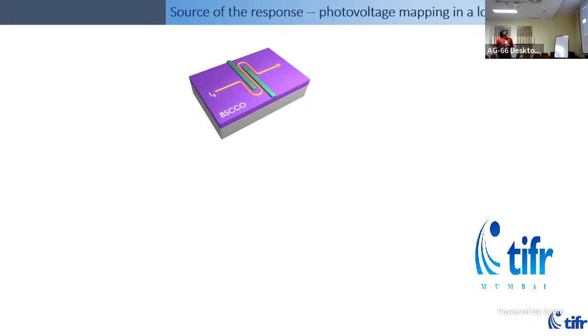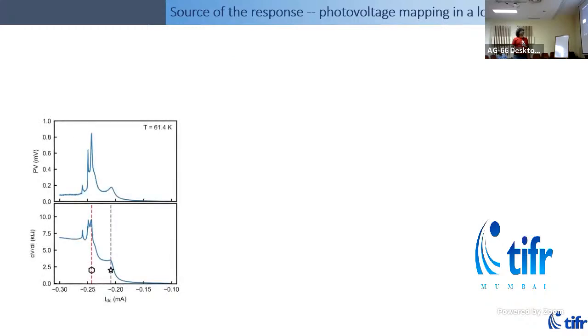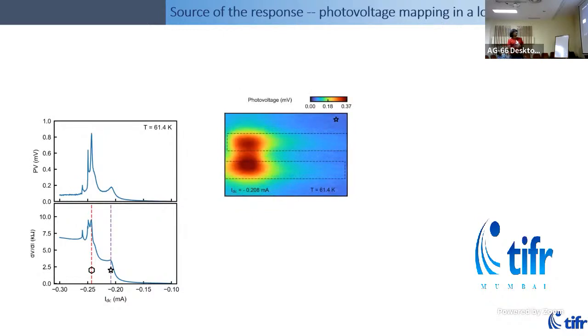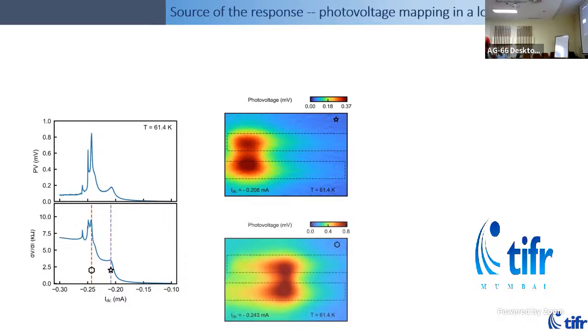So to understand what is the source of the photo response, we tried to do measurements on this wire as a function of space. So this is one unit of our bolometric detector. We can raster light at different points inside this. We bias it at a particular point by sending DC current through it, and then we measure this photovoltage response. So this is the insulating region. This is the chromium deposited on it, and we can measure the photo response as we move. So this is the extended film of BSCCO. There is no bolometric response. Only in the narrow wires you see a strong bolometric response.